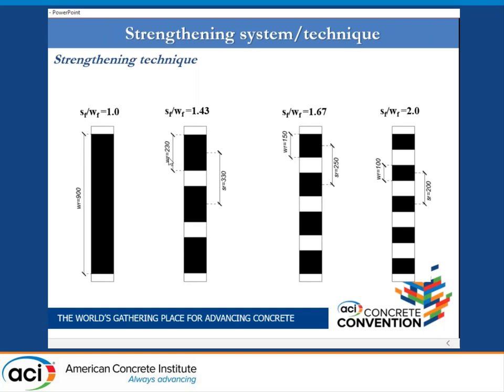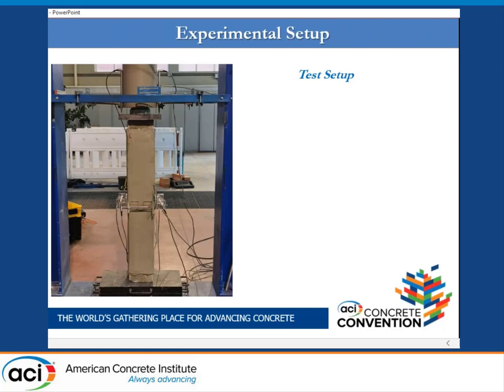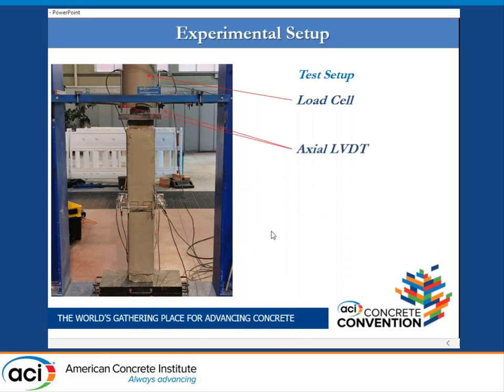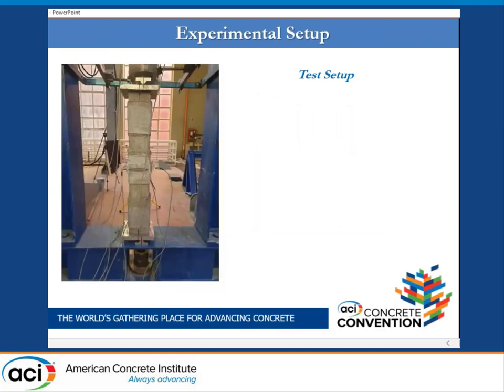Along the column, the lengths reported are in millimeters. In this figure, the test setup is reported. In particular, at the top of the column a load cell was applied to ensure axial displacement control. The lateral strain was measured on each side of the column by four LVDTs. The eccentric load was obtained by an eccentric connector, as shown in the figure, illustrating the load eccentricity and the column axis.